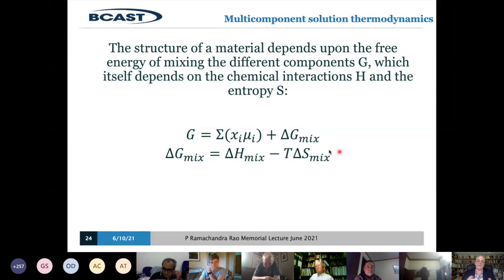Well, when you have a material with lots of components, this gets a bit bigger and it's more likely now to dominate over the energy of interaction between the atoms. So you don't get so many compounds forming and you get more of these large-scale, multi-component, single phases. And that's why you get the structure that I've talked about.